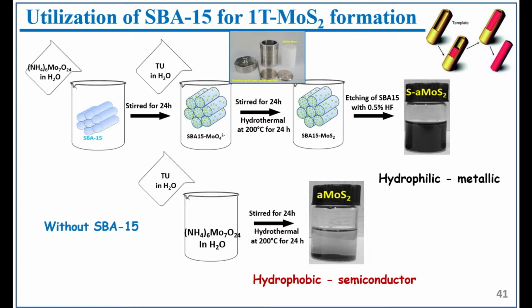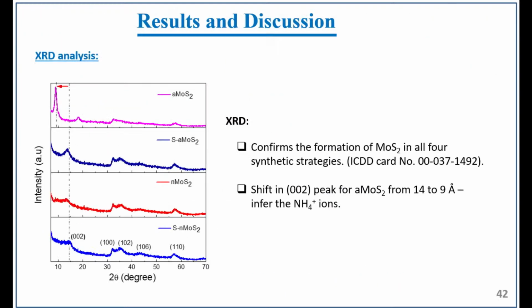So this is called sodium molybdate MoS2, and then in this case, ammonium molybdate MoS2. In the case of SBA-15, this is ammonium molybdate, this is pure ammonium molybdate MoS2. So if you go for XRD, we can see that in all the cases we are producing MoS2 with a good crystalline nature. The only thing is, in the case of ammonium molybdate, the slight change in the peak position shows that there is a slight entrapment of the ammonium cations in between two layers. So it's confirmed from the XRD shift, and all the other things are very well matched with the standard data. So in all the cases we are having MoS2.